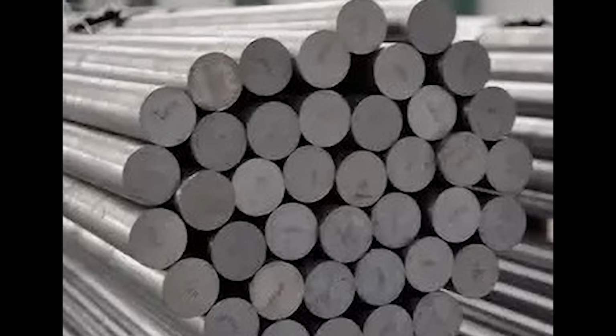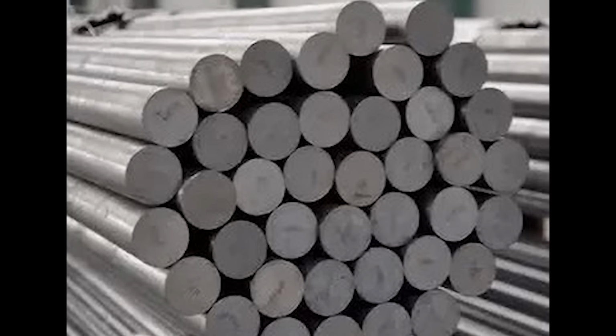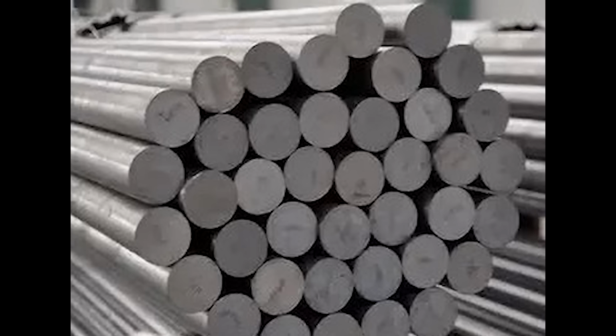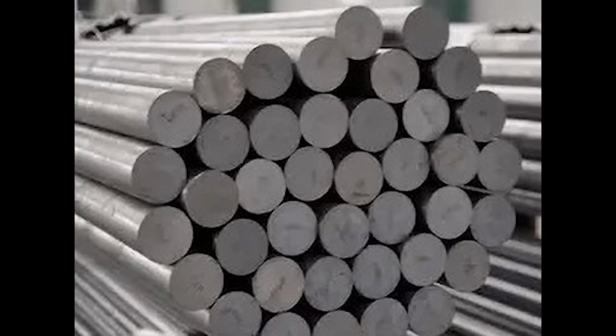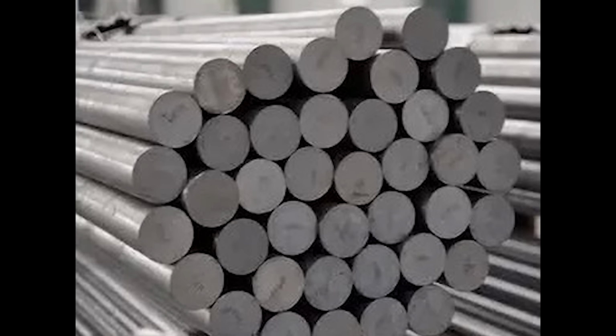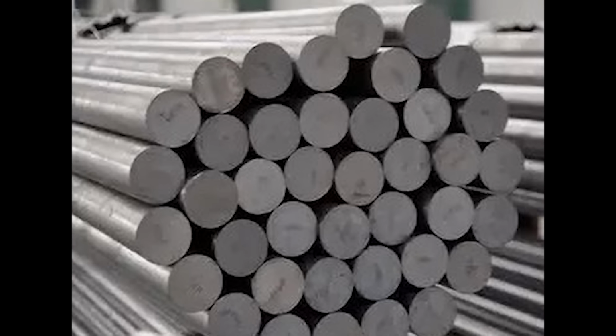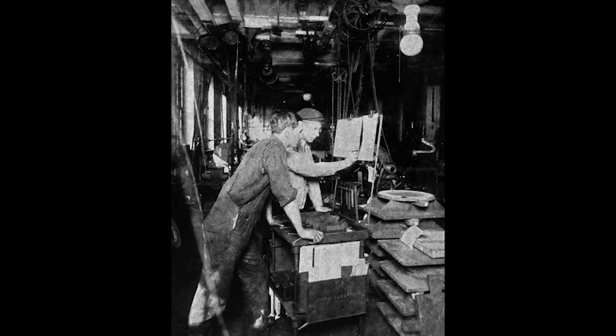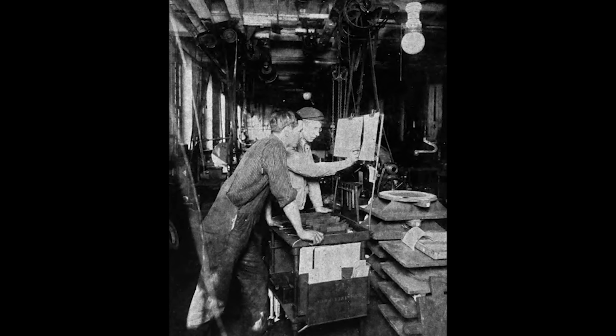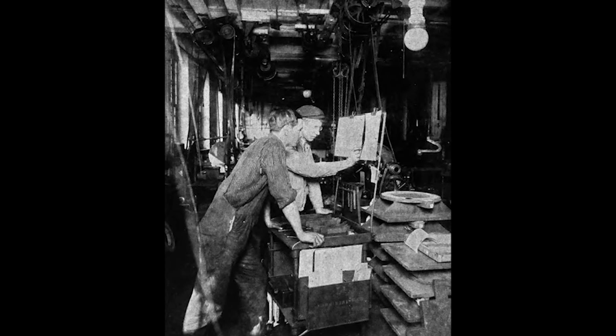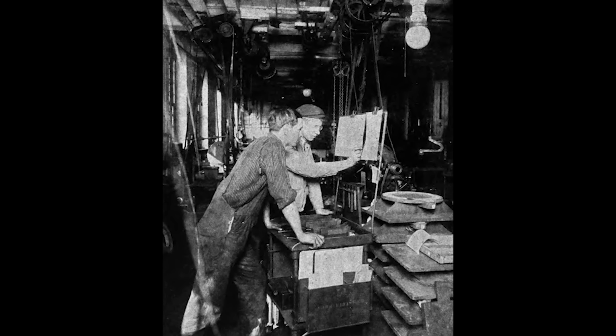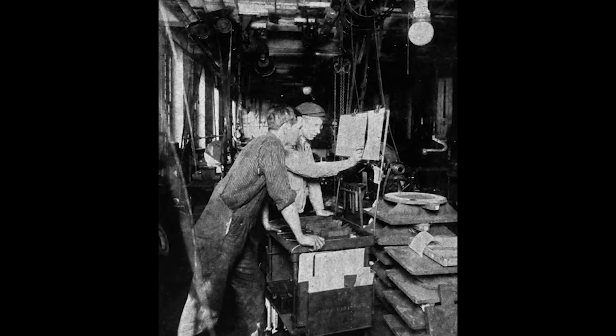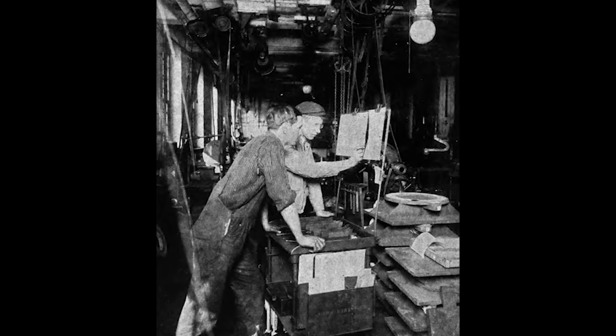Each batch of Taylor white steel required individual attention from skilled furnace operators who could judge temperature by color and adjust heating cycles based on furnace behavior. The pyrometer technology that enabled precise measurement was expensive but available. The tungsten required for the steel composition was more costly than conventional alloying elements, but represented a small fraction of the productivity gains the new steel enabled. By summer 1900, Taylor was confident he had solved the fundamental limitation that constrained American manufacturing productivity.